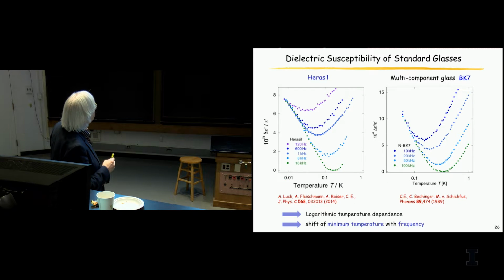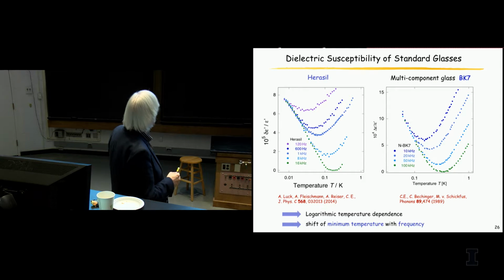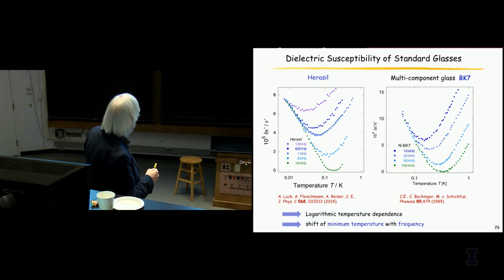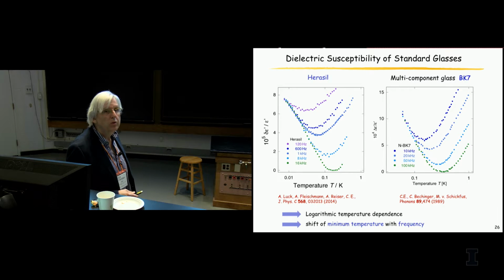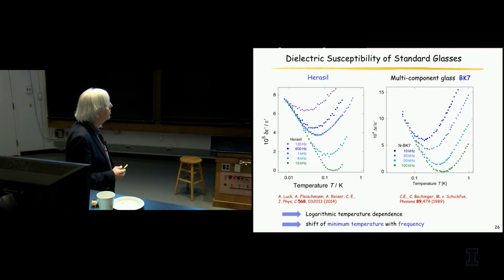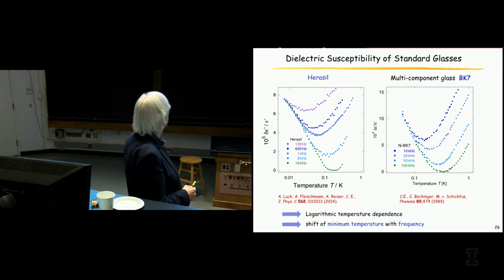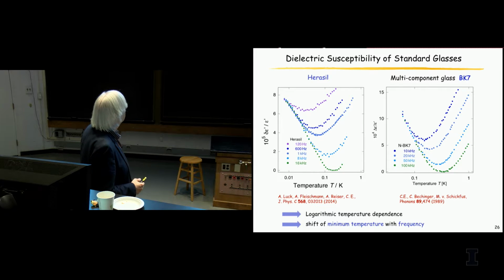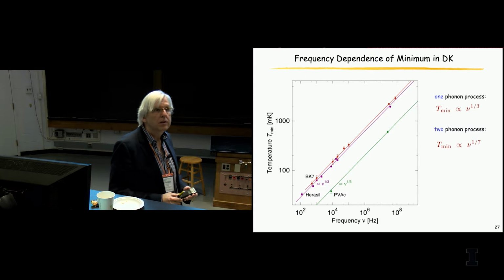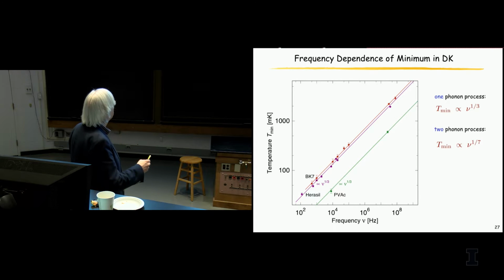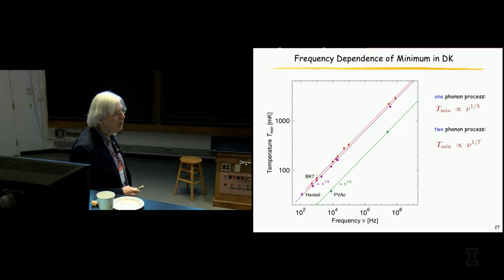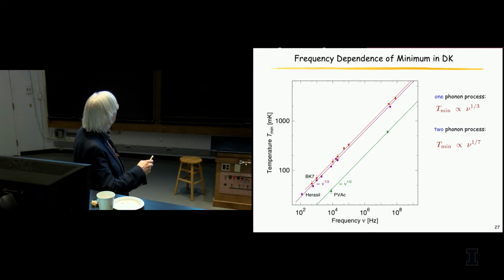So we measured first these standard glasses, Herasil. This is just a SiO2 glass. You see perfectly what the tunneling model predicts. It shifts the minimum to higher temperatures when you increase the frequency. And that's also true for the system BK7, this optical glass. That's long known. Then we quantitatively analyzed that. We did this measurement over a very wide range of frequency up to the gigahertz range. And you can see all of those points, the minima as a function of frequency, fall on this line. It's the one phonon process.